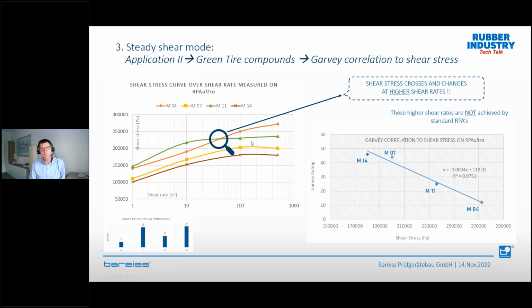When we go up to 500 reciprocal seconds, a very, very high shear rate, then we have the nice ranking of Garvey again. So you see on the left side, we have our shear stress at high shear rate compared to the Garvey ranking. We get a very nice correlation. All compounds that are flattening at higher shear rates are good in processing, and those which are increasing more and more at high shear rates are very bad in processing. So this is the first method and the first results we saw in industry, that we can really simulate the processing behavior of compounds with this steady shear method on the RPA Ultra.